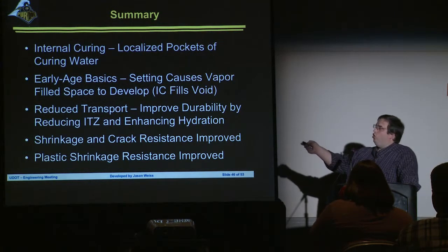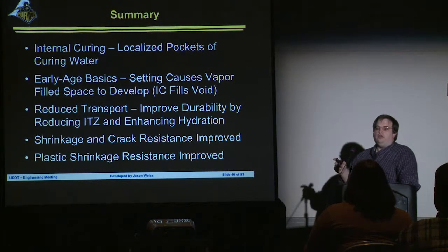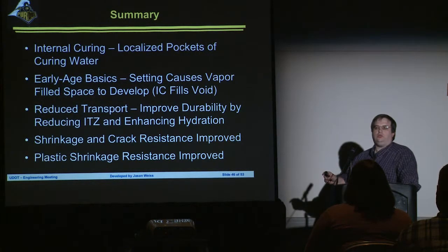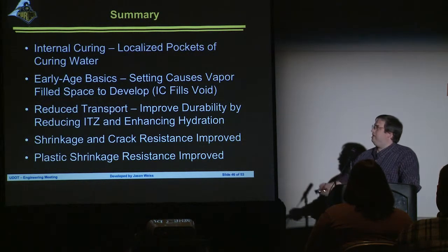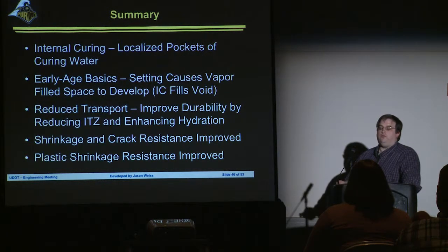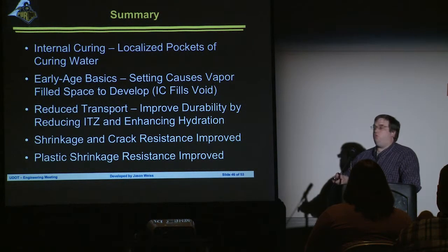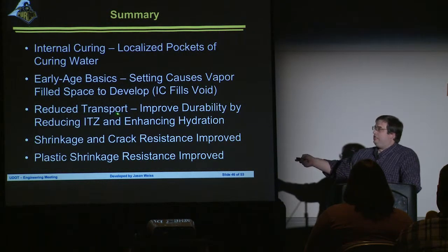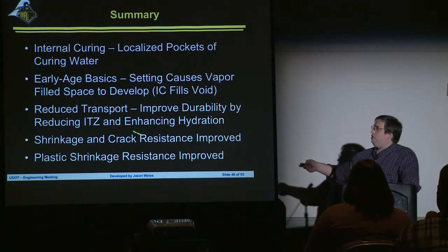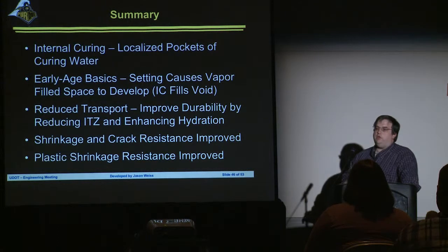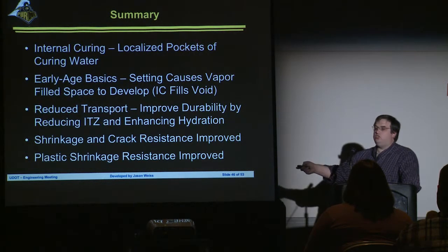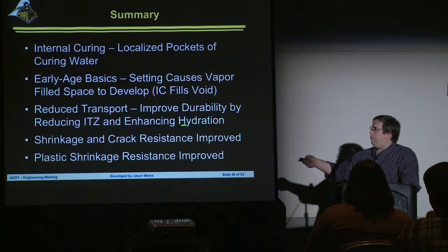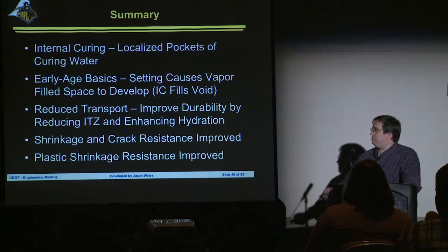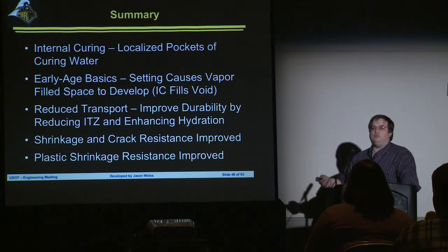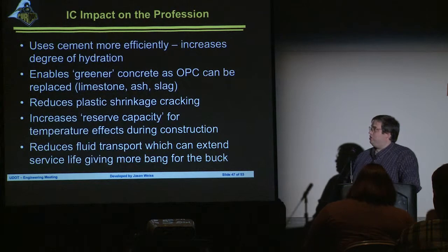Internal curing, localized pockets of curing water that are going to do exactly the same thing we did with external curing, but they're going to do it inside of the concrete. Setting causes these vapor-filled spaces to form. What we want to do is fill them with water from the lightweight aggregate. In addition to reducing shrinkage and cracking, we can improve our transport properties. We can increase durability because we've reduced the interfacial transition zones and we've increased the hydration that happens in the system. And we also see benefits in terms of thermal change and plastic shrinkage cracking.